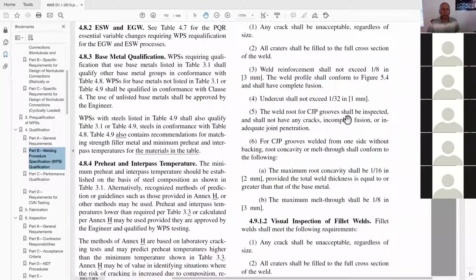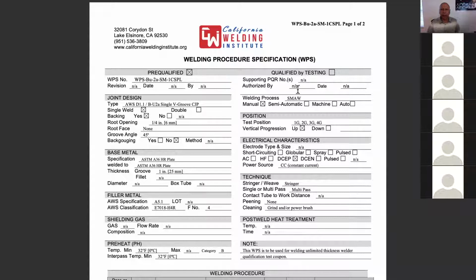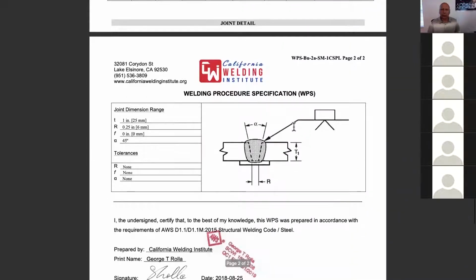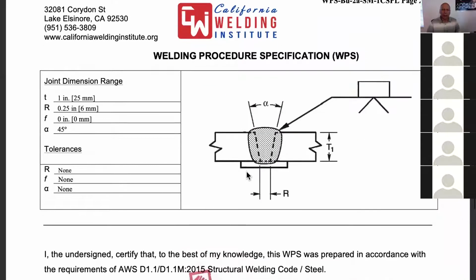Keep in mind that the weld root for a CJP groove weld shall be inspected, and must not have any cracks, incomplete fusion, or inadequate joint penetration. If we look at the test coupon, how are you going to inspect the weld root if you have a steel backing? Well, you can't. Most people think that you inspect the root pass from this side.